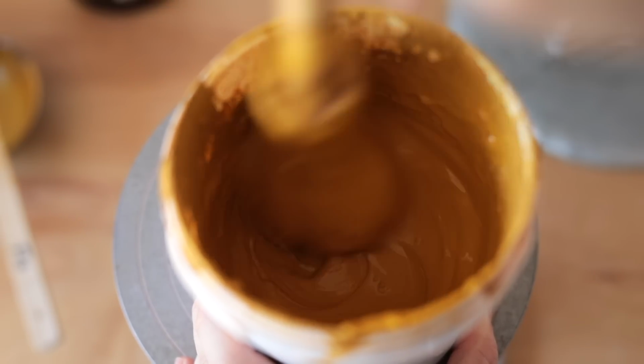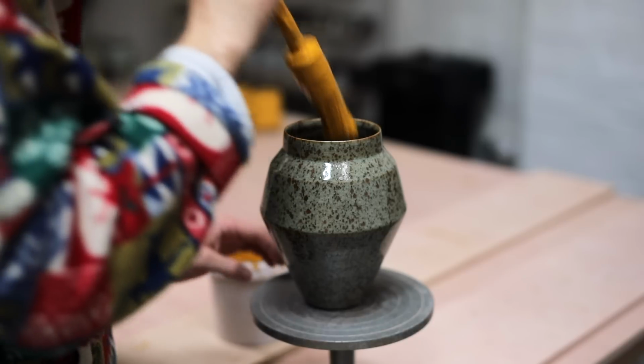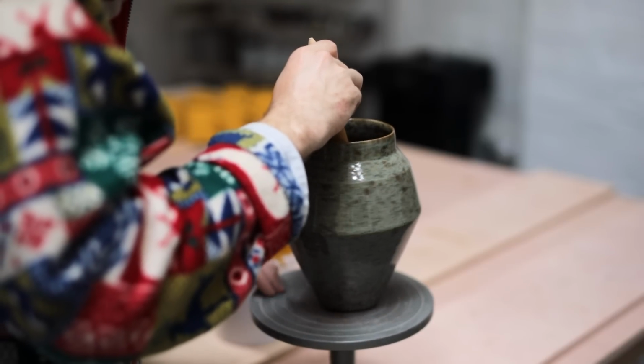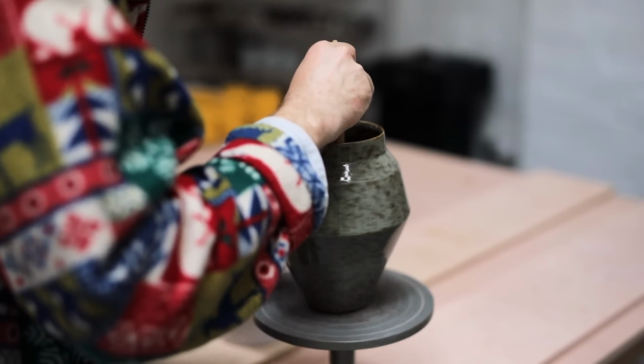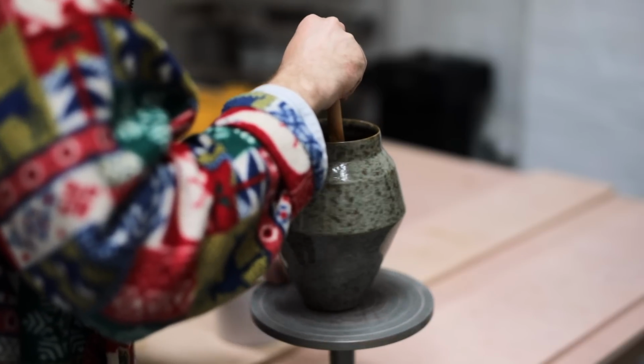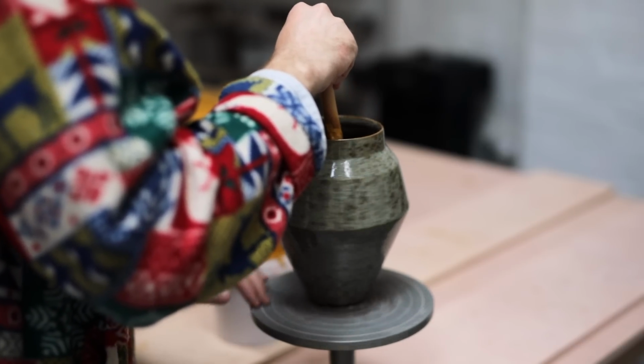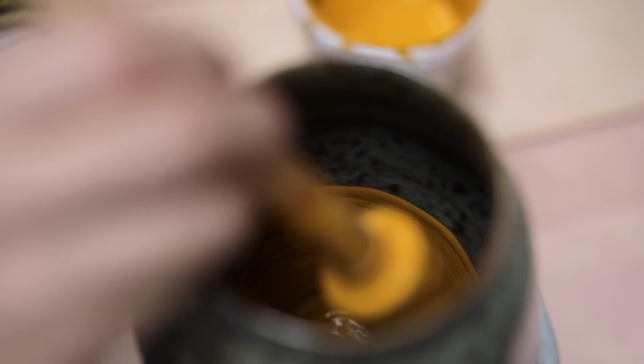I simply mix this with a tiny bit of water until it makes a thick slurry, which I then brush onto the pot both inside and out. This isn't necessarily something new I've been doing, and if you've been following along on my Instagram, or if you've watched my shorts here on YouTube, you will have seen me do this to pots already in order to potentially save pieces I don't like. It works especially well on bowls, as they have a simple, curvaceous interior into which all this extra metal can melt and flow, mixing with the glaze underneath to create something new. But this is definitely the largest piece I've tried this technique with, nor have I ever tried it with a pot that contains so many iron spangles.